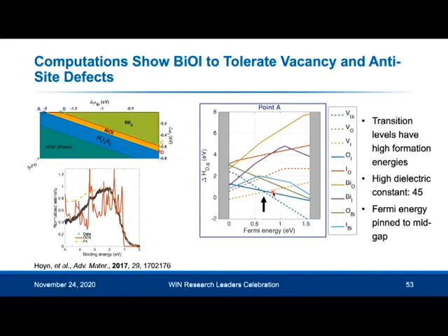We're looking for the Fermi energy in which there's a change in the slope. These are called transition levels, and that's where the defect state can trap an electron or hole to change its charge state. So you can think of these as where the traps are within the band gap. And what you can see here is that for these lowest formation energy defects, they don't have these traps within the band gap. Or if they do, they're shallow.